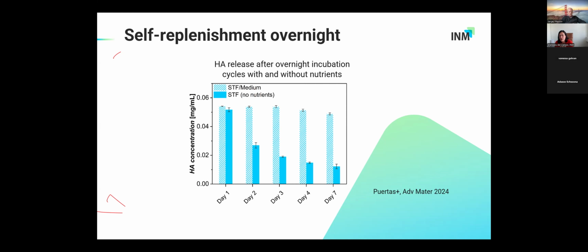What we have here are two different types of experiments. In one experiment, we have kept the lens during the night in simulated tear fluid without nutrients. Okay, so it's only buffer. And in the other case, we have incubated the lens during the night in simulated tear fluid with medium, which is closer to what we really have in the tear fluid. And then we have done this for several days. So we have incubated during the night and measured or detected hyaluronic acid release during the day.